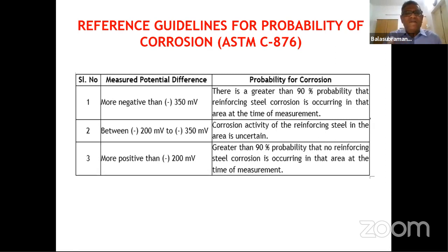That's the only case where we want to use this half cell potential test, because in any corroded area there is no point, as obviously we'll get a value more negative than minus 350; we may get minus 500, minus 600. So generally we use this test in a large structure only in the good areas, so that we know the visually good locations are really good from the corrosion potential point of view. That helps us decide on the bill of quantity required to do the rehabilitation. This is the half cell potential test.